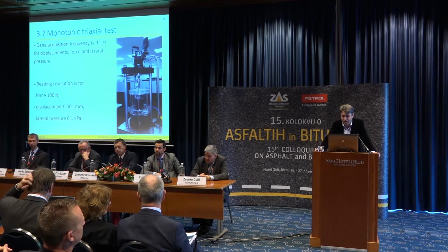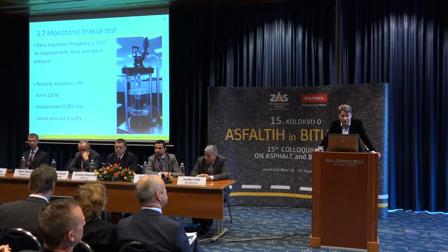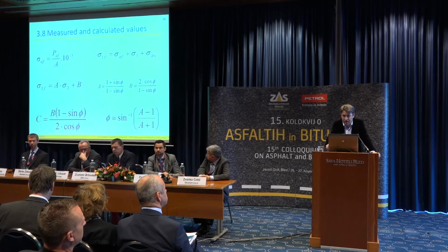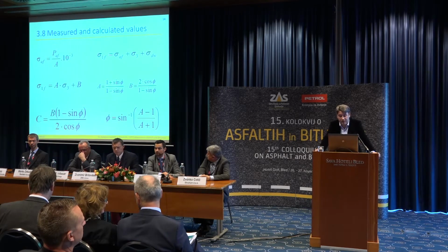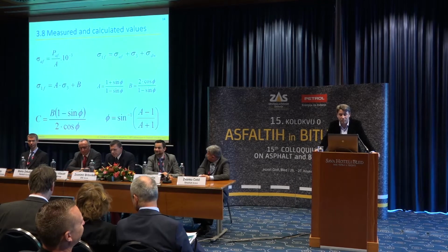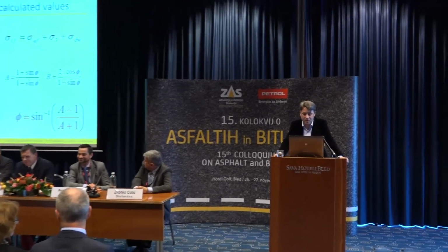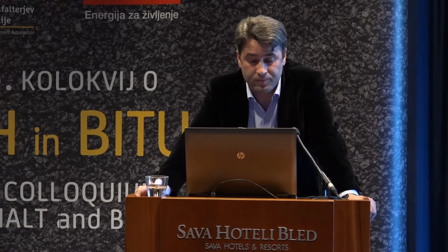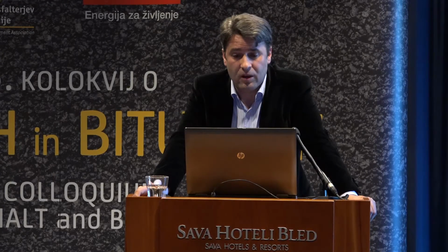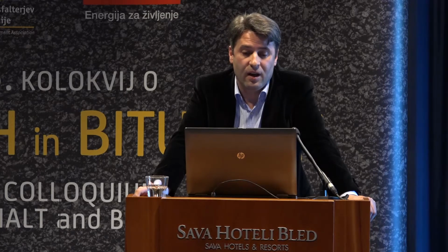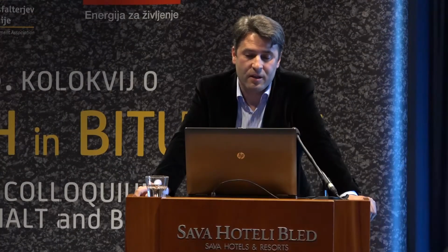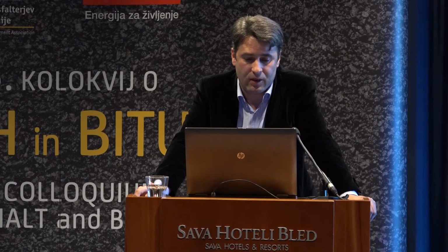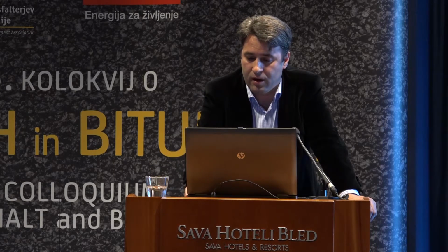Just one more slide on that. Now, I know that when you show a slide like this, you lose 50% of the attention of people, but just to get an overview, what we do is we measure the compressive strength of a material, and then, doing a linear regression combined with the sigma 3, you come to the cohesion and internal friction angle.